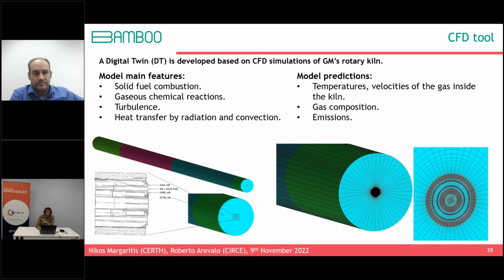So the way to produce this digital twin is to first produce a CFD simulation of the rotary kiln. Here you can see just a few features of the simulation. You can see the geometrical model that we have set up for the rotary kiln, and you have the physics that we introduce in this simulation. We simulate the combustion of the coke or the biomass. We simulate also the gaseous chemical reactions. We take into account mixing by turbulence, heat transfer by radiation and convection.